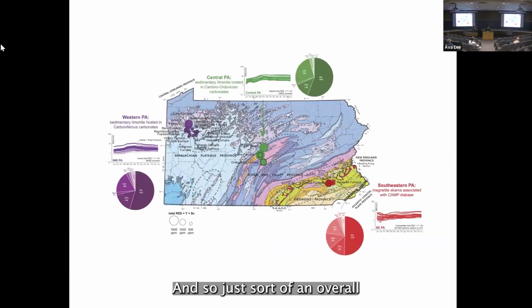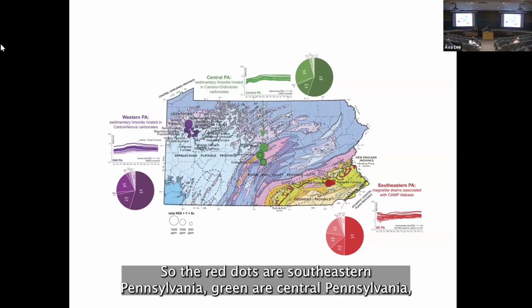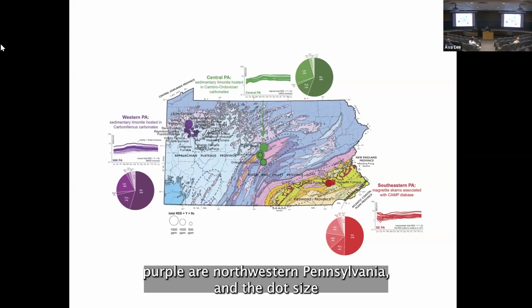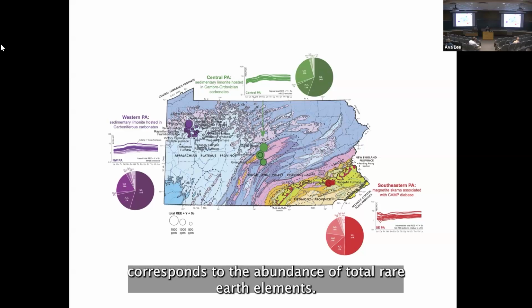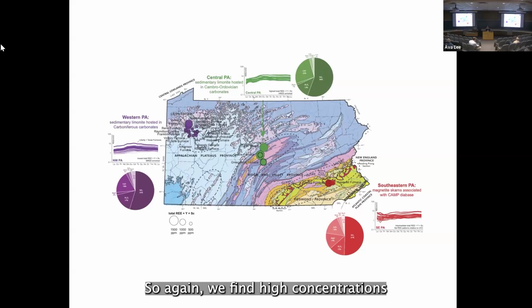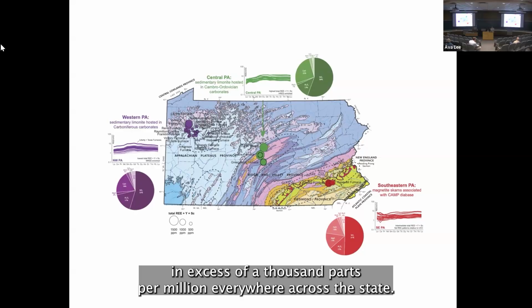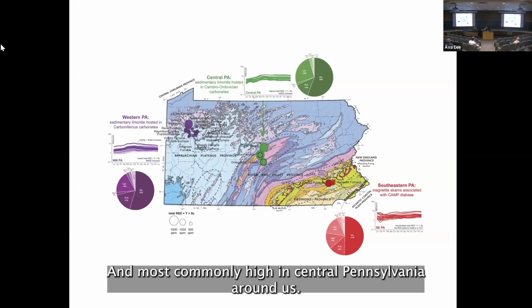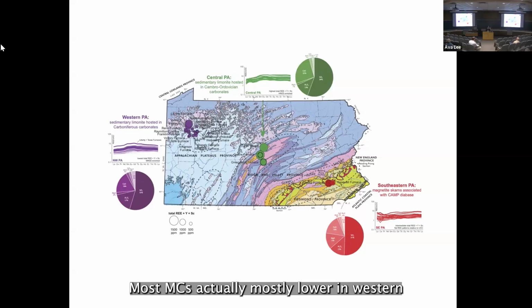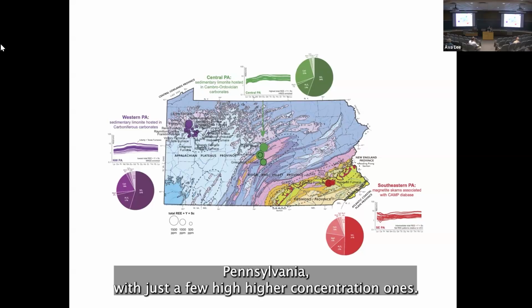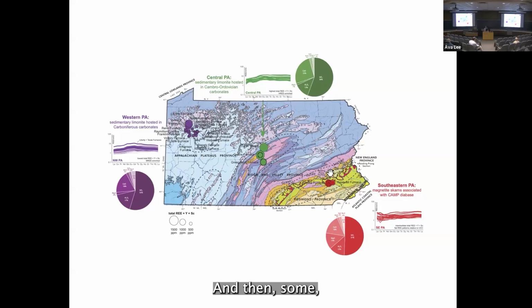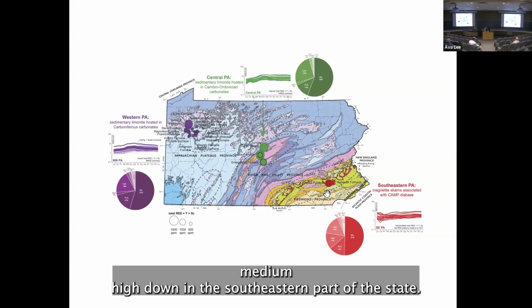And this is just sort of an overall summary of what we know so far. So the red dots are southeastern Pennsylvania, green are central Pennsylvania, purple are northwestern Pennsylvania, and the dot size corresponds to the abundance of total rare earth elements. So again, we find high concentrations in excess of 1,000 parts per million everywhere across the state, and most commonly high in central Pennsylvania around us, mostly lower in western Pennsylvania with just a few higher concentration ones, and then some medium high down in the southeastern part of the state.